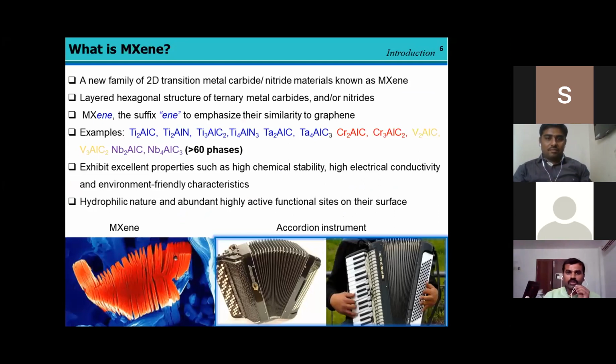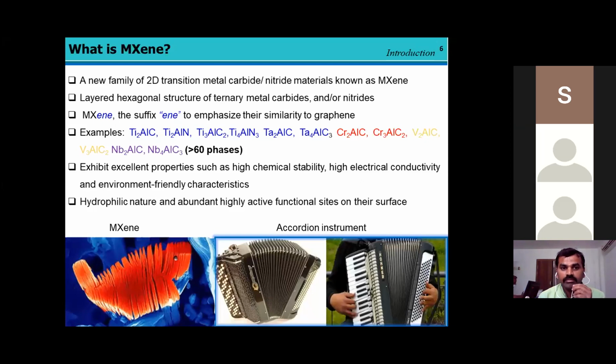MXene is nothing but a 2D material. As I already said, it has the layered hexagonal structure of metal carbides and metal nitrides. The suffix "ene" in MXene emphasizes the similarity to graphene, hence the "ene" comes from the graphene material. More than 60 phases of MXene material have been obtained. Most of them are titanium-based, and chromium, vanadium, and niobium-based, which exhibit properties like high chemical stability, high electrical conductivity, and environment-friendly characteristics. It is hydrophilic in nature and has abundant, highly active functional groups on the surfaces.